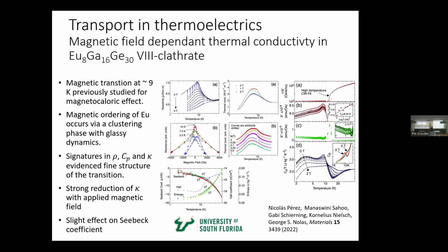In this case, it's europium, which is magnetic and gets ordered, and we assume that the magnetic ordering is not just between the europium atoms by themselves, but there's some degree of mechanical or magnetoelastic coupling to the lattice or to this volumetric cage structure, leading to a strong reduction in the thermal conductivity, which is then interesting by itself. Collaterally, or in the course of these investigations, we did the full program. We measured resistivity, Seebeck coefficient and heat capacity.